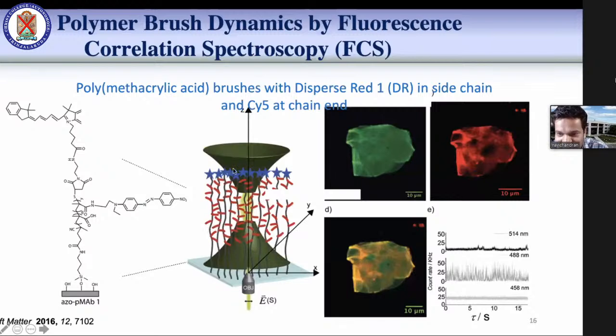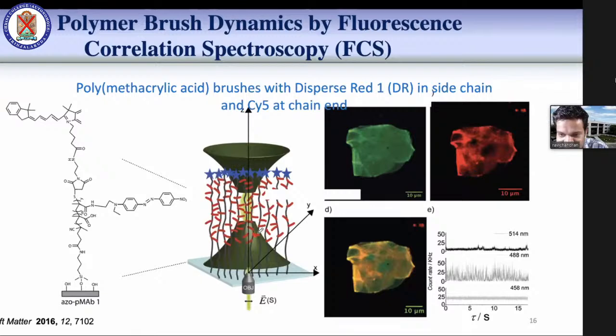This is the optical view of how it looks. We have polymer brushes, and we have a side chain, which is azobenzene molecule, and the main chain. On the top of the chain, we have another dye, which is called Cyanine 5. This is excited at 633 nanometer, and this is excited at 488 nanometer. So when we excite these molecules, this undergoes photoisomerization, and this is the confocal volume.